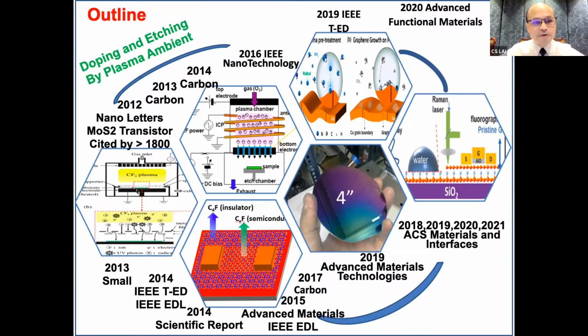And for the first figure here, that's for the plasma doping. We just using the plasma ambient with a filter. The filter is silicon material, and it's transparent, but we just coating with carbon, with metal to just prevent the UV irradiation to 2D materials. And we also try to using these special techniques for doping, including fluorine and nitrogen, to perform the insulator or semiconductor, a semiconductor from graphene itself to a little bit opening of the band gap.